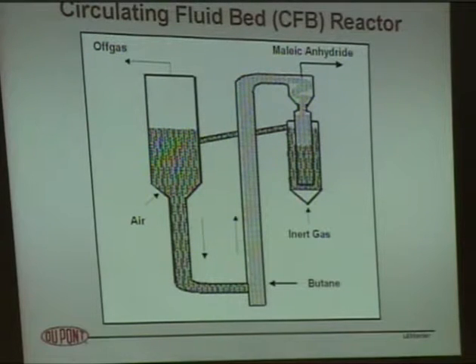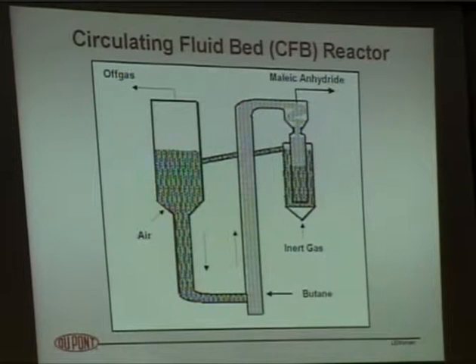So here's the schematic of the circulating fluid bed reactor. Butane is fed in the bottom along with the vanadium pyrophosphate catalyst. Comes up through the riser. The VPO catalyst reacts with butane to make maleic anhydride that's separated. The reduced catalyst comes out of the reactor into a cyclone. The cyclone then sends the reduced catalyst to a separate fluid bed reactor where it's reacted with air to regenerate the oxidized catalyst, which goes around the loop.